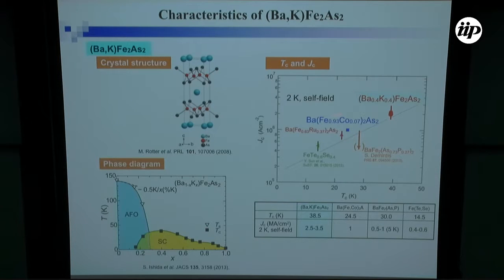As I said, there are several systems we can work on, but today I will exclusively show data on this best crystal, 122 crystals, which is barium 0.6, potassium 0.4 crystal, with TC higher than 38 Kelvin. Even in the pristine state, JC is roughly 3 mega-amps per square centimeter. The one thing we should note is that all these iron-based superconductors do not have any correlated defects, because in the case of YBCO, we have twin boundaries, which can mimic the effect of columnar defects. But in our system, if there are correlated defects, that is solely from columnar defects.